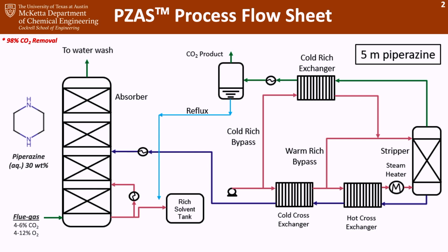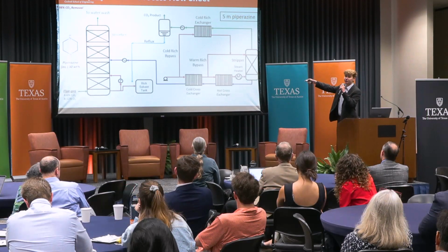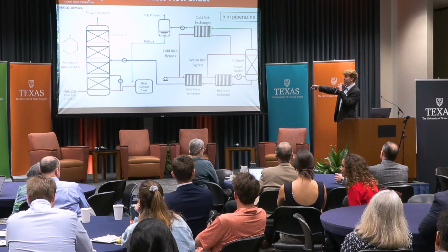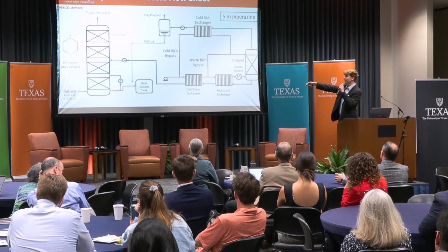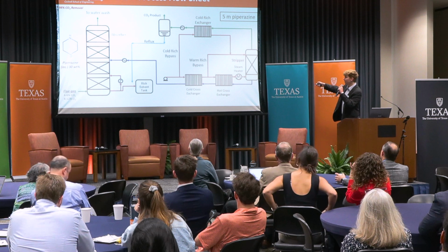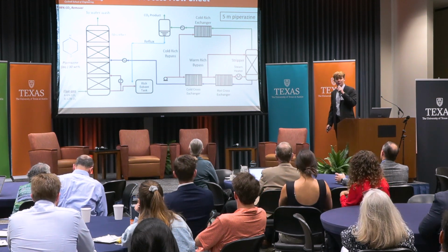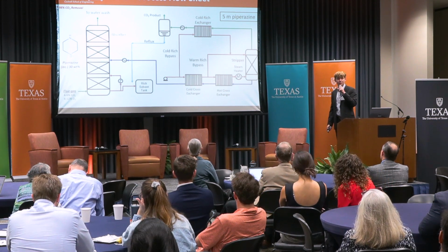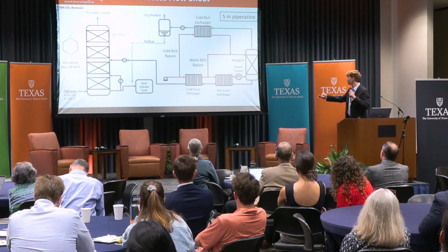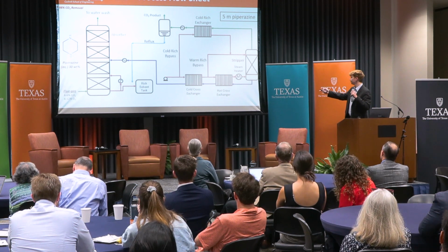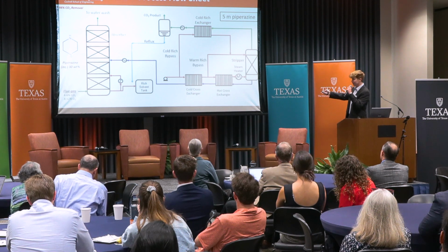Following the absorber process, we then move on to the stripper. This is a temperature swing process in which this newly reacted piperazine and CO2 will then dissociate in the stripper, resulting in piperazine being recycled into the process and CO2 moving on to the next stage. You'll be accumulating some sort of degradation, both oxidatively in the absorber and thermally in the stripper. And so liquid and gas phase analysis is incredibly important for understanding what our degradation products are in those two phases. I think I'm having some technical issues.